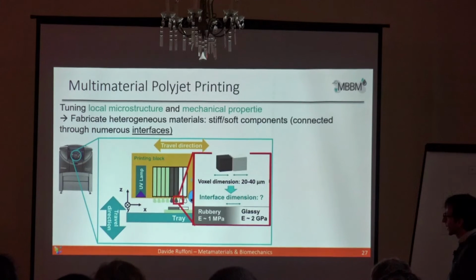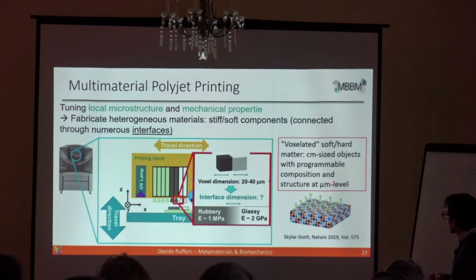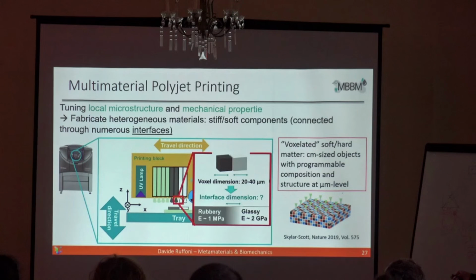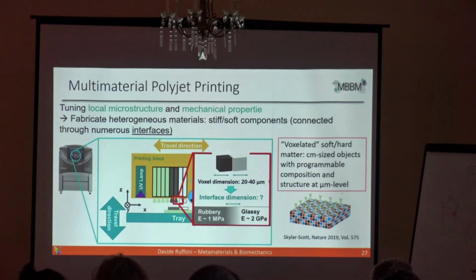But what is nice with this technique is that we can locally tune microstructure and mechanical properties to fabricate what we call voxelated soft-hard matter. So we can obtain centimeter-size objects with a programmable composition and structure at the micrometer length scale. This is why we got quite interested in this technique. It can print structures with voxels of 20 to 40 micrometers, which have very dissimilar mechanical character. We can have soft, rubbery voxels with 1 megapascal tangent modulus, and glassy voxels up to 2-3 gigapascal stiffness, and we can combine these in infinite types of arrangement.